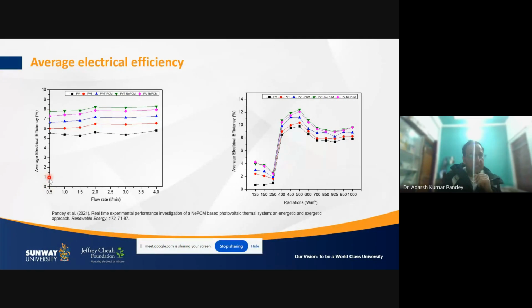This is the average electrical efficiency. If you see here, we did the PV study at Kuala Lumpur, from 0.5 liter per minute to 4 liters per minute, and you can see that the average electrical efficiency was roughly 5.5% when PV alone, but when the PVT collector is there, it goes more than 6%. And when we attached the PCM into PVT, using the dual application, you will find that it goes more than 6.5% average electrical efficiency.